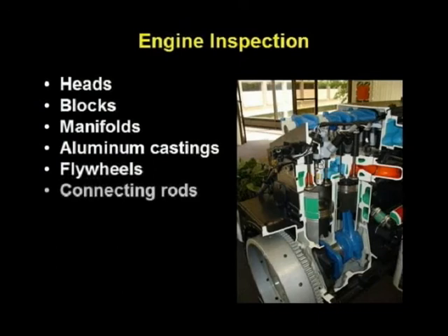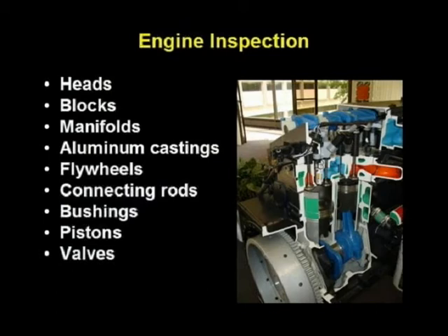Connecting rods are inspected by magnetic particle inspection, and the residual stress is measured by X-ray diffraction methods. The bushings in connecting rods are inspected for contact between bushing and rod using ultrasonic immersion C-scan inspection. Aluminum pistons are inspected for debonding between cast iron ring carrier and the aluminum. Inertia welds on valves, steel pistons, and turbocharger wheels have been inspected using ultrasound. Valves have also been inspected for cracks in the stellite facing using eddy current methods.